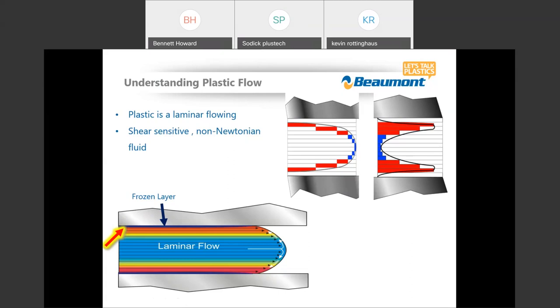And the reason we know that is that the highest Reynolds number that we can achieve with plastic flow, with the least viscous olefin going through the tiniest gate at the fastest velocity, is something on the scale of 10. And if we understand what the Reynolds scale is, what that is describing is when a substance obtains turbulent flow, like for instance, water can obtain turbulent flow because it can reach a Reynolds number of 4,000 or higher. So when we reach that 4,000 Reynolds number, we then are entering a turbulent state.